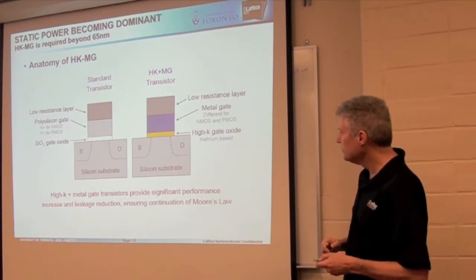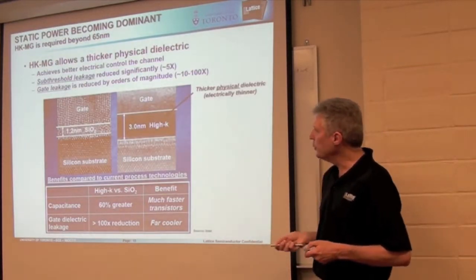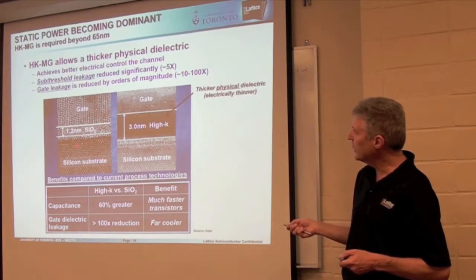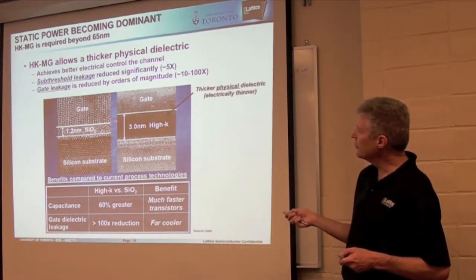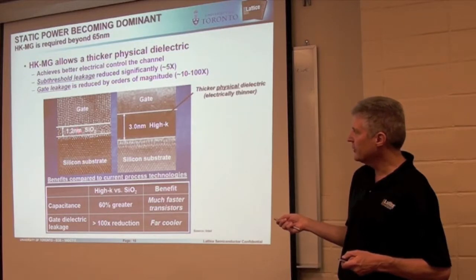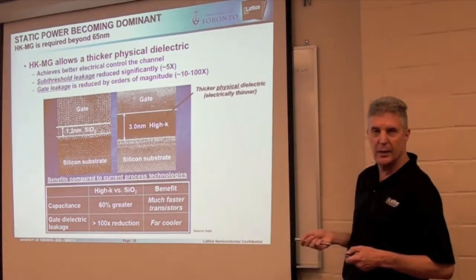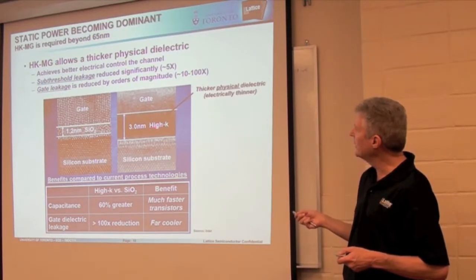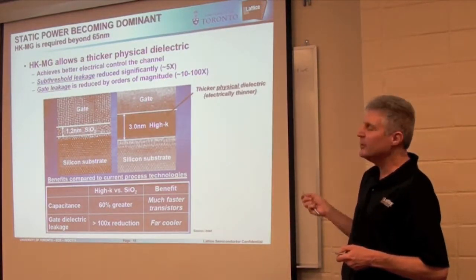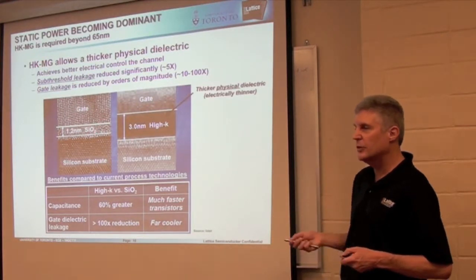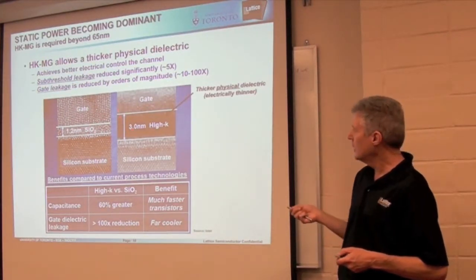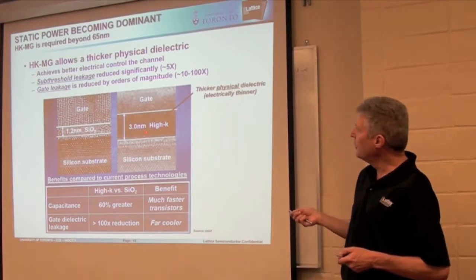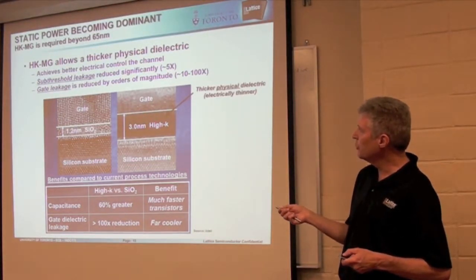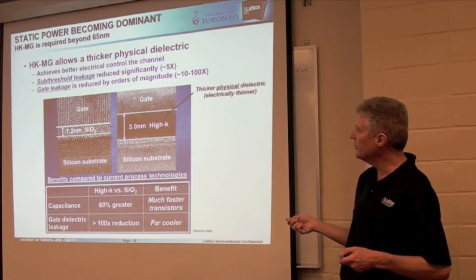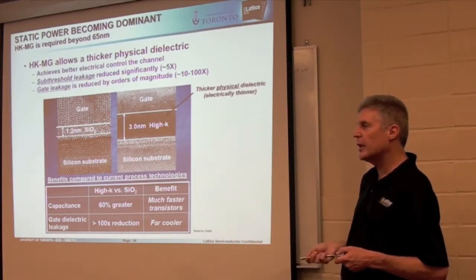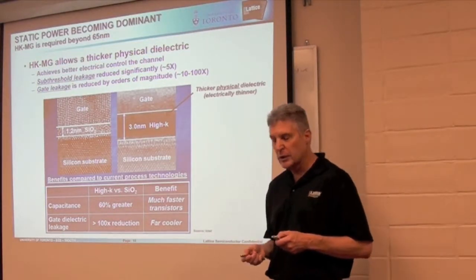thicker material. So again, looking at the real geometries here, this is the previous transistor we looked at. This is a HighK metal gate. You can actually, instead of having 12 angstroms of oxide, you can have 30 angstroms of HighK hafnium-based gate oxide, and even though it's thicker physically, it is electrically thinner than the silicon dioxide due to the dielectric constant. So this benefits you in terms of improving subthreshold leakage by coupling more directly to the substrate, and gate leakage by having a thicker dielectric that will not punch through and allow leakage current into the substrate.